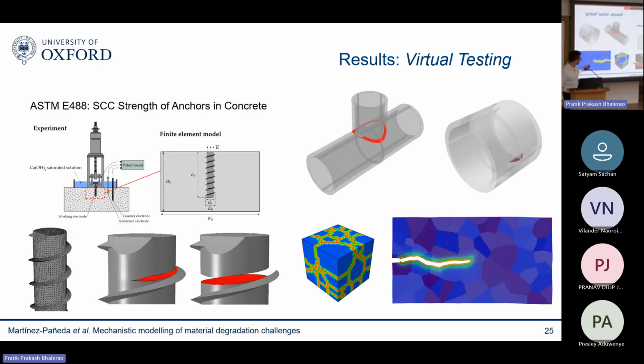So we recently started doing a lot of work on crystal plasticity, the coupling with crystal plasticity and microstructural modeling. Traditionally, this was not of interest to the hydrogen embrittlement community because they were looking at very aggressive conditions where you had already big cracks to start with. But now when hydrogen compatible materials are being considered for aviation, there's a lot of interest in looking at what happens, how do you initiate a fatigue crack, for example. So in microstructurally driven problems, we're starting to do crystal plasticity and couple with these models. But you can also do, of course, large-scale simulations.